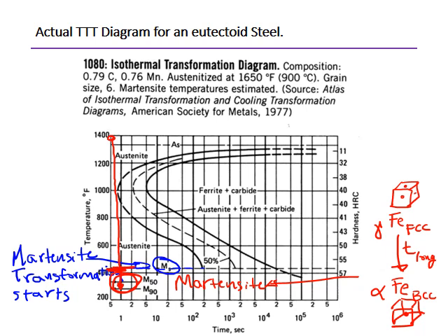But when you are quenching, you have very little time. So the crystal will not be able to accommodate the atoms which are at the faces to other places. So these atoms won't have time to travel and to create the body center cubic crystals.